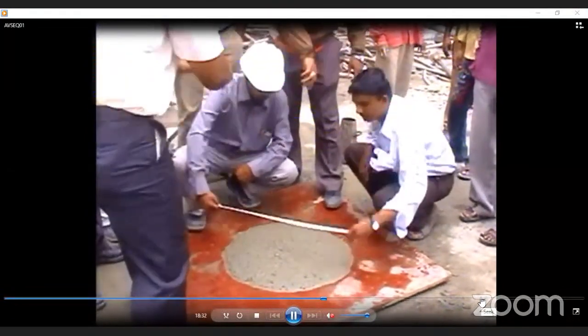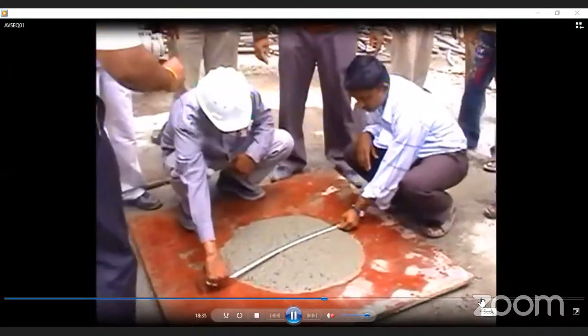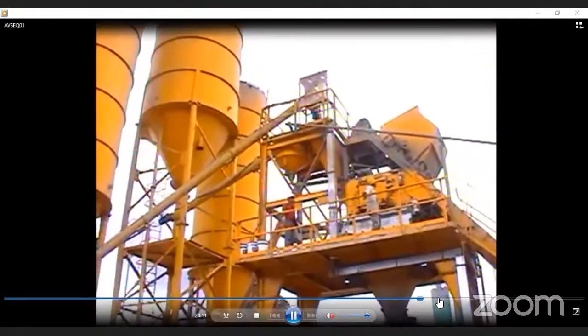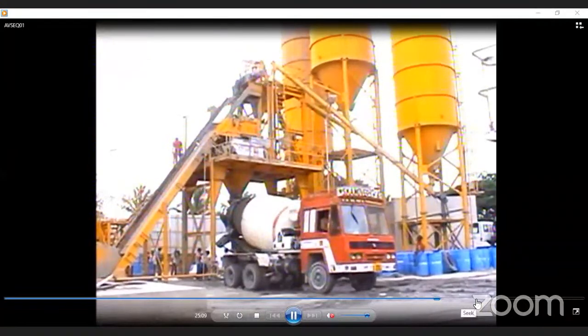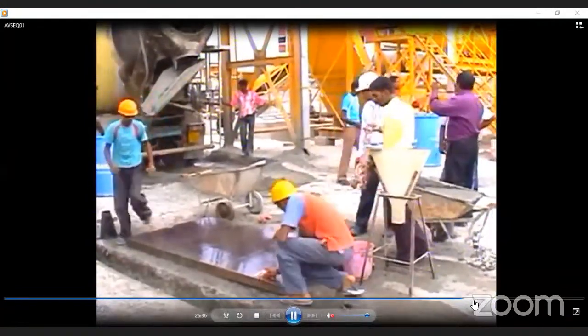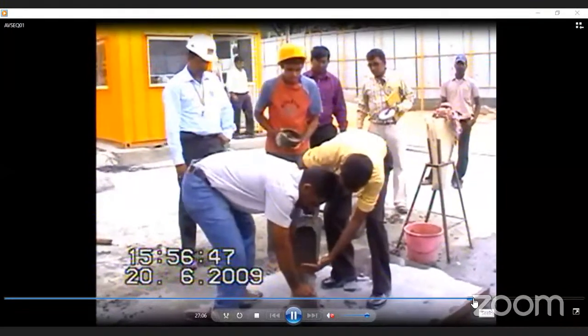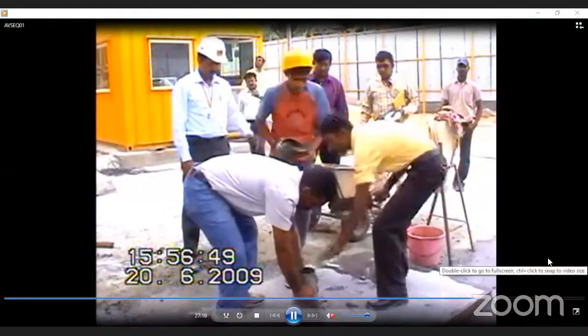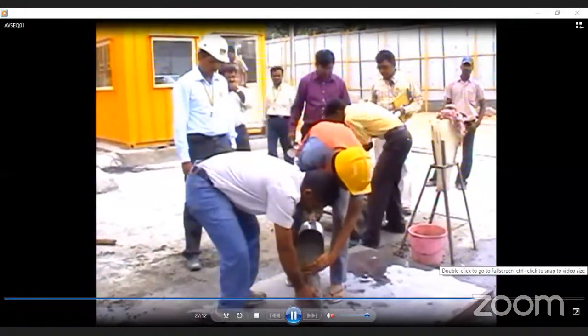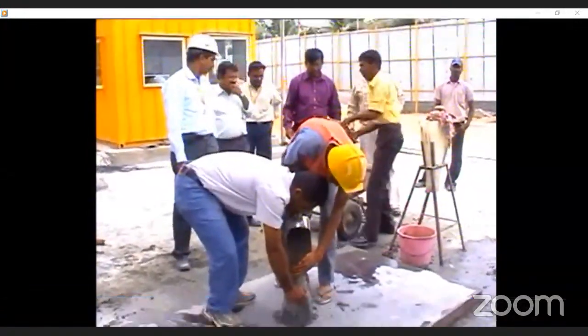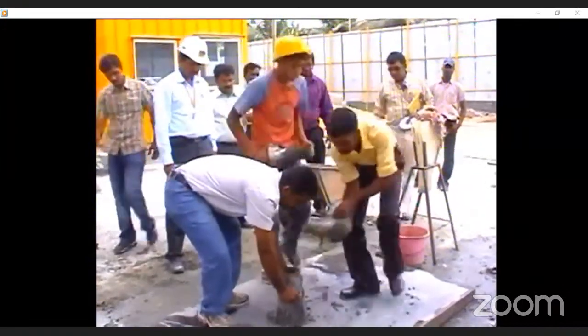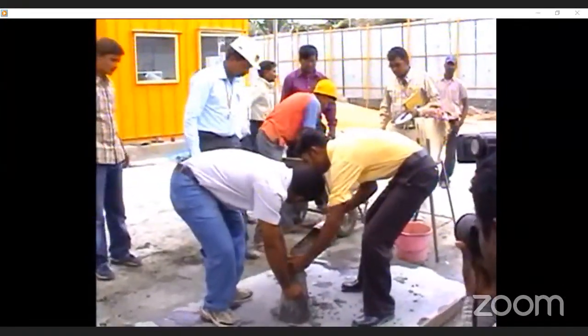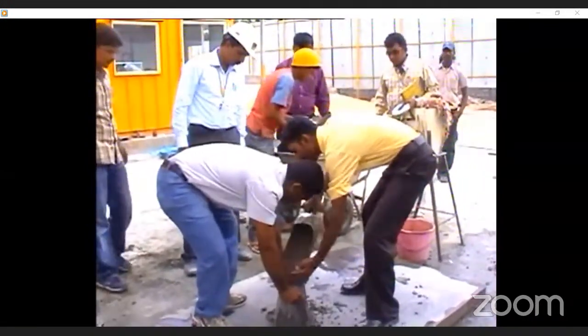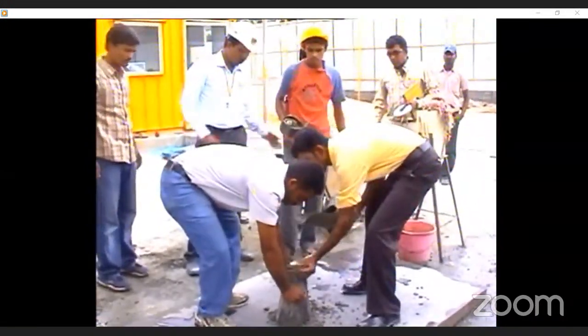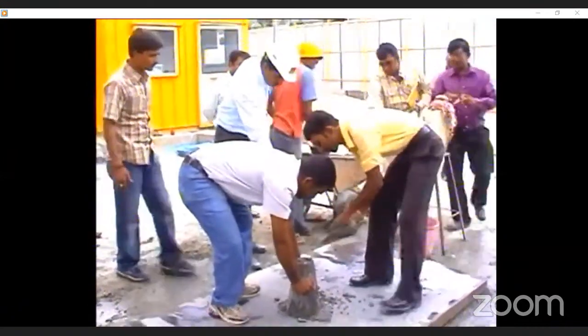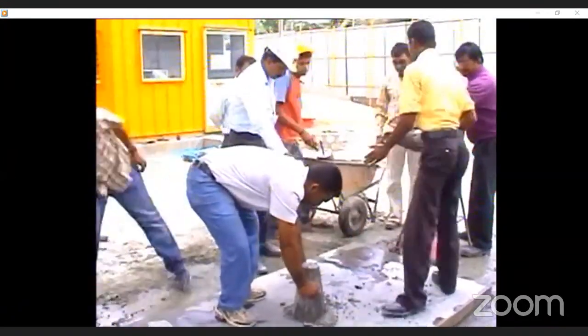Now, we checked not only at the site, we also checked at the plant. We did the V funnel test as well as the flow table again. It's a very sensitive concrete. The mixing time should not be more than 30 seconds. If the mixing time is more than 30 seconds, even though you added the air entraining agents, it will lead to the burst of the air bubbles, and the air entraining agent will not have any effect. Care must be taken, even with the mixing time.